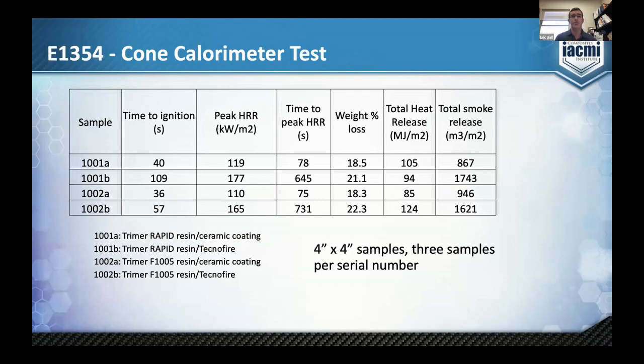So here's kind of a shortened summary of those tests. If you want to look at total heat release, you can see that the Tecnofire did a better job overall, even though it produced a little bit more smoke than the ceramic. But when we look towards the E119 test, it's really more important to prevent temperature and burn through.